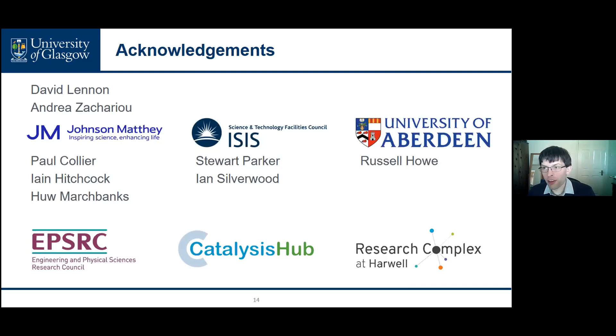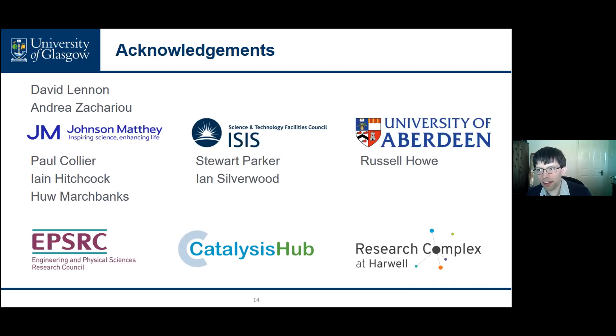It's a good question. Generally speaking, anything that has significant levels of hydrogen in it is going to be a star candidate for INS analysis, because the scattering cross-section of hydrogen for INS is huge, so any hydrogenous species are always going to stand out extremely well over the background. It also works fairly well on quite a lot of other catalysts. David has done extensive work using it to analyze Fischer-Tropsch synthesis, so generally anything with hydrocarbon production is a fairly good candidate.